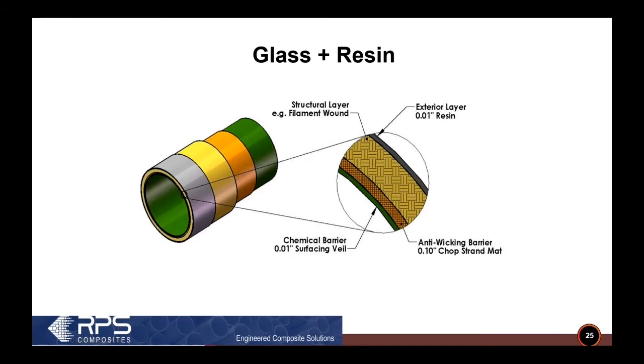And then behind that, we typically put a couple of layers of that chopped strand mat, and that combined with the chemical veil gives you a lot of corrosion resistance and a lot of resin. Behind that, we need to have some strength. So we either use the glass filaments or a combination of the chopped strand mat and woven roving to get you a higher glass content in the structural layers, where you might have between 50 and 70% glass.